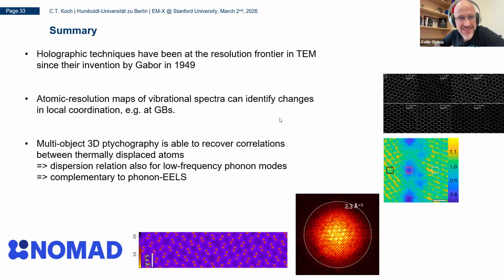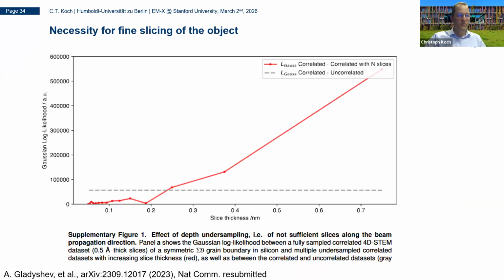Just one last slide. Yeah, while you're pulling it up, I would love to see 2 Laue rings, and maybe I would become a believer. Okay, this one is from this arXiv paper, in the supplementary material. It turns out if you use slice thicknesses of 2 angstroms and less, you stay below this error metric, the Gaussian log likelihood that Anton used for this ptychographic reconstruction. If you make your slices thicker, like 2.5 angstroms, the error starts going up. So only with 2 angstrom slices do you get good agreement between experiment and simulation. 1 nanometer is basically out here to the right, so you have to use very thin slices to get this good agreement.